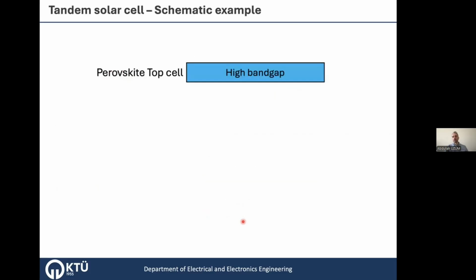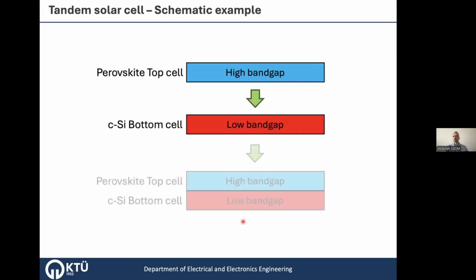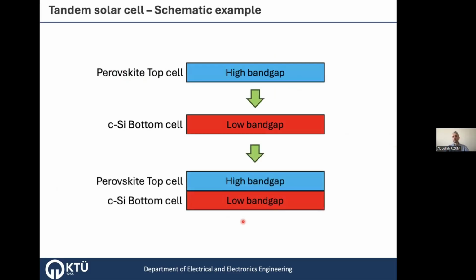So in this part, I will show you some earlier tandem studies and recent tandem studies. One of the earlier tandem studies was carried out when I was a postdoc, so I will give some examples from that time too. This is the thing we did at that time, back in 2015. We used the perovskite top cell as the high band gap solar cell and a crystalline silicon bottom cell as the low band gap bottom cell. And you have this kind of structure, right? But again, the most important thing here is the recombination junction. The junction at this interface is very important. We will talk about it from now on.